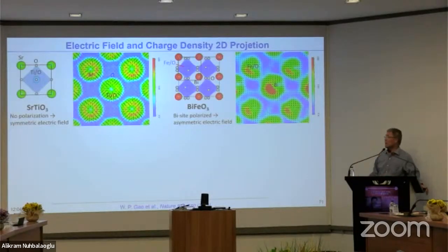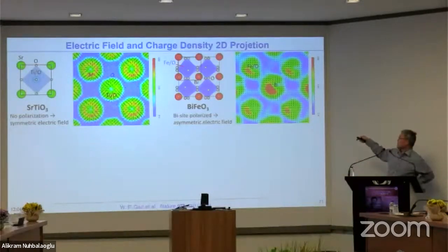All right. With this method, we demonstrate charge density measurement for two different materials. One is strontium titanate, a prototype with a similar structure but a different kind of ferroelectric property. This is not ferroelectric; it's symmetric. This is not surprising, a very nice symmetric field distribution. But for the ferroelectric bismuth ferrite, the polarity, as I mentioned earlier, is along the body diagonal direction. You can see that this polarity is very clearly demonstrated in the field map.